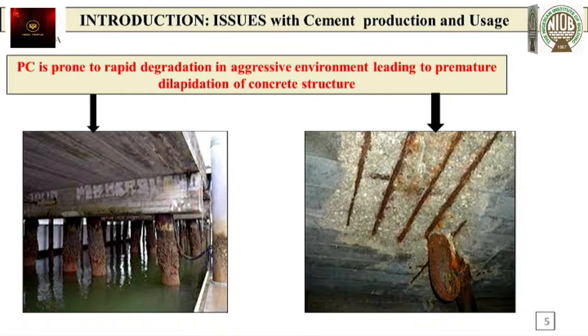Now, this issue that we have with the production of Portland cement, also, this product is prone to degradation in an aggressive environment. As you can see in this picture, Portland cement is used in the production of concrete. When this is subjected to an aggressive environment, this is what we have. If you check our environment very well, if you observe our slabs, or an environment where you have ingress of moisture in concrete, where you have harmful minerals in the soil, once you have an ingress of water in your concrete, it triggers a chemical reaction where you have this peeling, and at the same time you begin to experience rust on your reinforcements. Next slide, please.